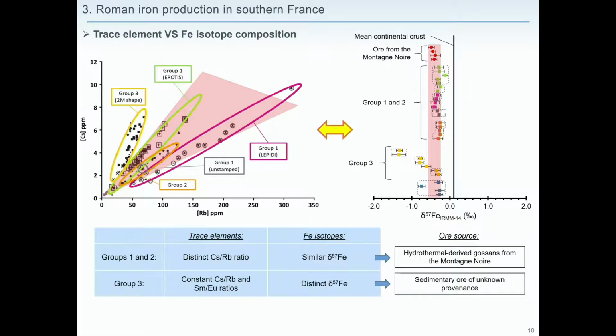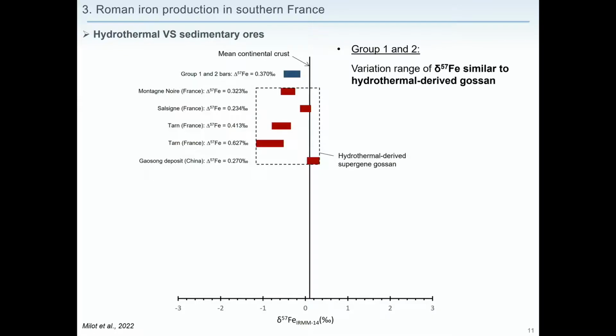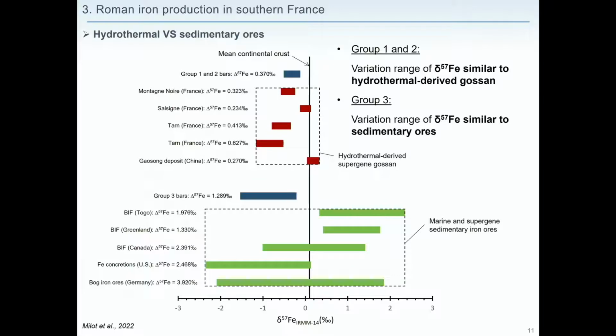And then we have the third group with a very constant trace element ratio, which argues for a single source for these bars, and in contrast, distinct iron-isotope composition. So it could seem in contradiction, but here we propose, in fact, that these bars have a single source of sedimentary iron ores. And it makes sense if we compare the variation range of these bars with that of different types of ores. Here you have the variation range of group 1 and 2 compared with different supergene gossan from different places worldwide, and they are of the same order. And in contrast, the variation range of bars from group 3 is much wider and is of the same order as different types of sedimentary iron ores.